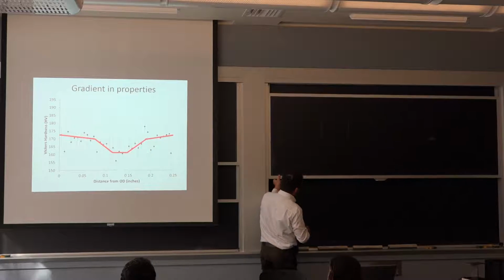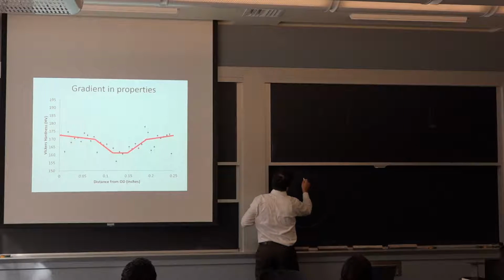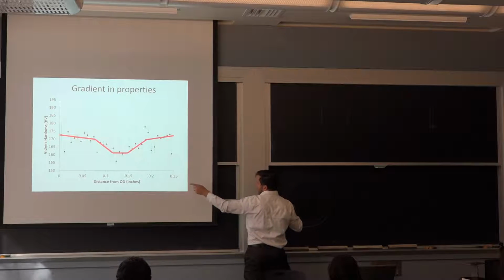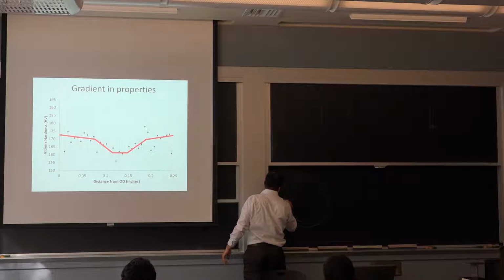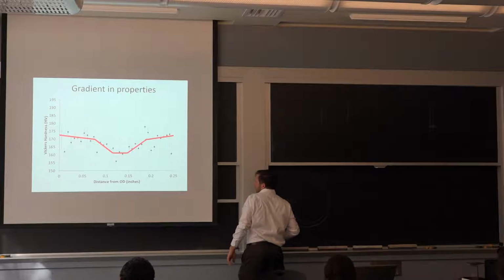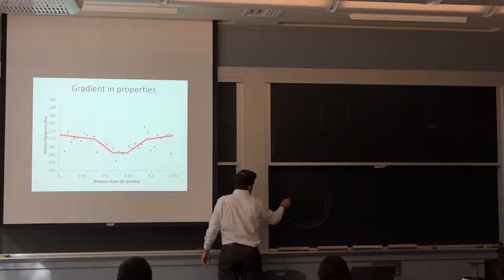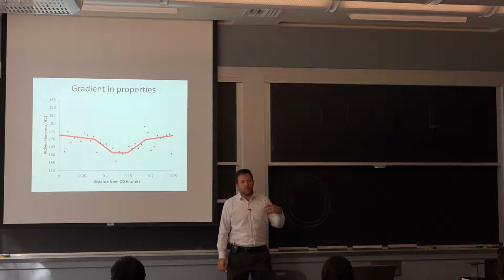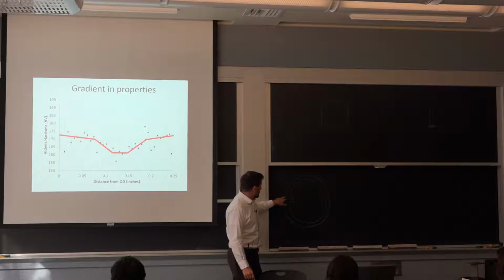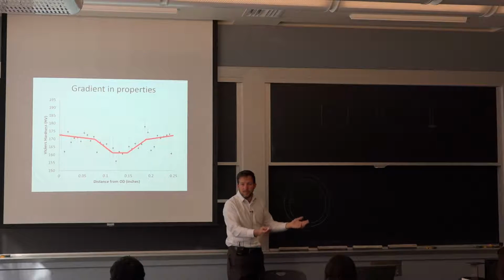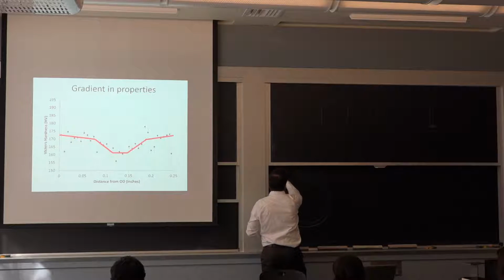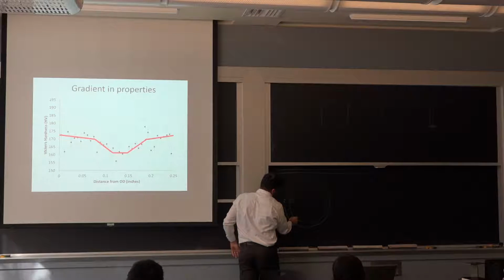So let's see. Here's the pipe. It's got a certain wall thickness, and the axis here is from 0 to 0.25. That's what we're looking at. So we see that the hardness is higher on the surface. It goes to a minimum in the center, and it goes higher on the other side. So if we don't know anything about what happened, we can essentially hypothesize, hey, because it's harder here, as I form, I essentially bend the plate, because this pipe came from a flat originally. It just essentially rolled and then seam welded here. So I have my weld in this area.